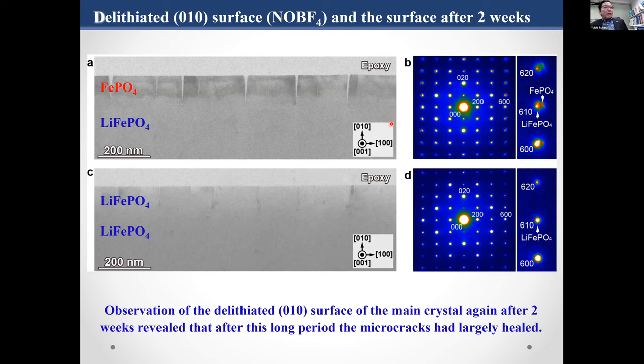Yes, this is a very important question. And I think this crack formation, of course, depends on the size of particles. Here we use a very, very flat single crystal surface. Therefore, the cracks are periodically, almost periodically located, but the distance between them is on the order of 100 nanometers.